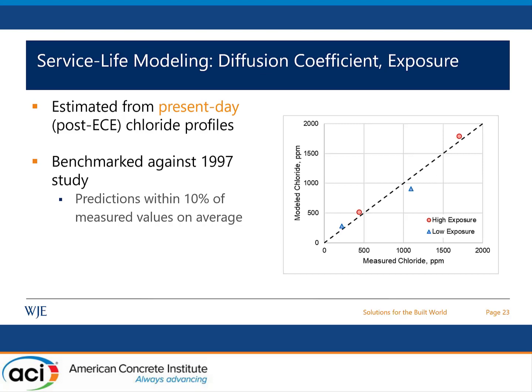So we had a couple cases that we benchmarked with our models. The first is the 1997 field investigation. There were powder samples drilled from the piers, and chloride concentrations were measured at depths between 0 and 1 inch and 2 and 3 inches. So we looked at our models' estimates of what the chloride profiles would have looked like in 1997 and compared those to what was actually measured on the piers. And we found that our predictions were within about 10% of the measured values on average, which gave us good confidence in our model.